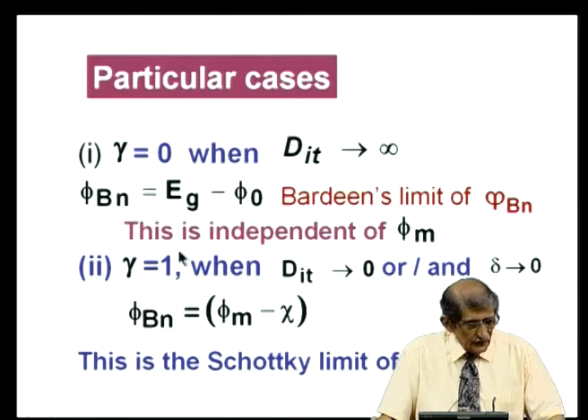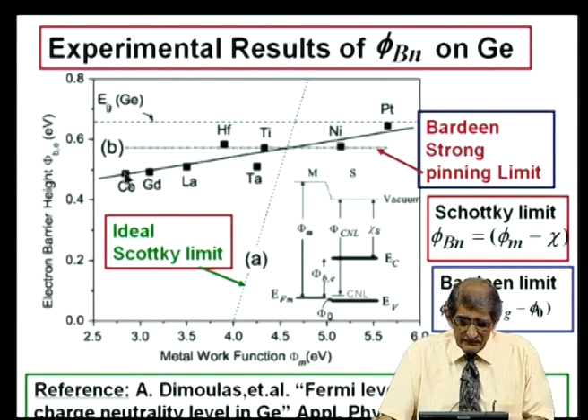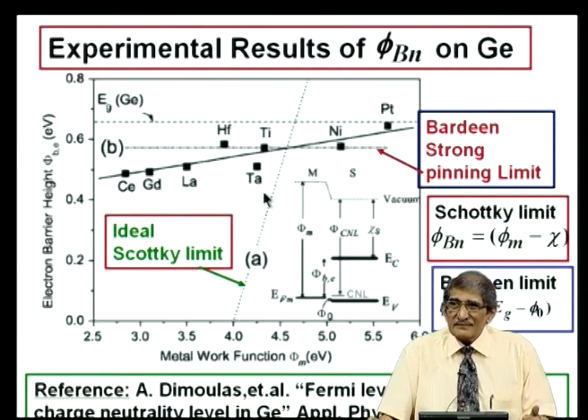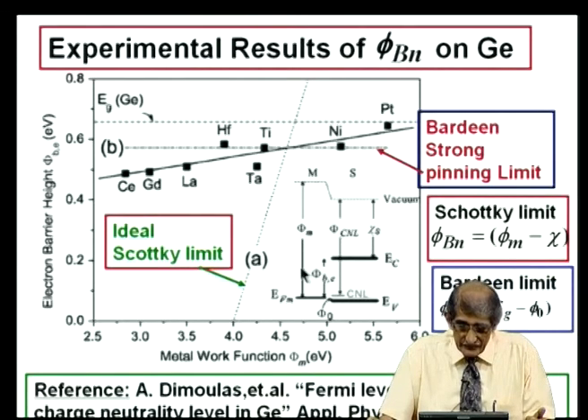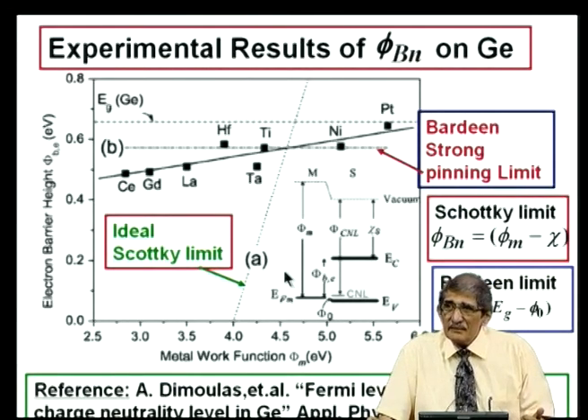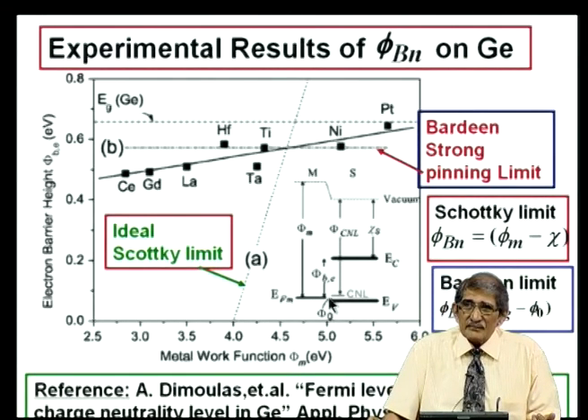Okay. So, this is what we showed for germanium. In germanium, you see, the barrier height for electrons was something like that, 0.66 is the band gap, and it was very close to the band gap there. When the phi_m is varied, there is very little change in the barrier height. So, in germanium, it is a hopeless situation to make an n channel MOSFET, because the barrier height will be very close to the band gap. Band gap is 0.66, phi_0 is 0.09, so very close to 0.6 electron volts. So, it will be a very bad situation to make an n channel device, but anything you deposit on germanium will make ohmic contact, because the barrier height is very small for holes.